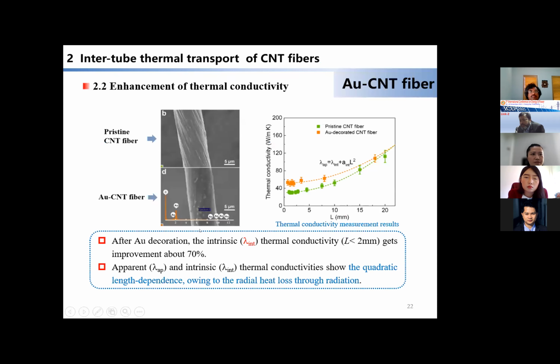After decoration, we tested the intrinsic thermal conductivity by our homemade 3-omega technique. From the results, we see that after decoration, the intrinsic thermal conductivity for lengths less than 2 millimeters improves by about 70%. The apparent and intrinsic thermal conductivity shows a quadratic length dependence owing to the radial heat loss through radiation.